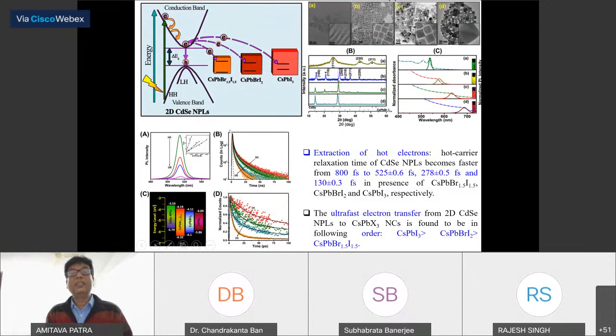This is another material with the perovskite. We want to see whether the extraction of the hot electron can be tuned by the perovskite. This is the perovskite nanocrystal, and we have seen the extraction of hot electron carrier you can control from 800 femtosecond to 130 femtosecond, because this is very important to understand your design of the device, so that your efficiency you can enhance because of the ultra fast electron transfer process. So these are the fundamental things we try to understand. I will not go into the detail, but I'll give it.